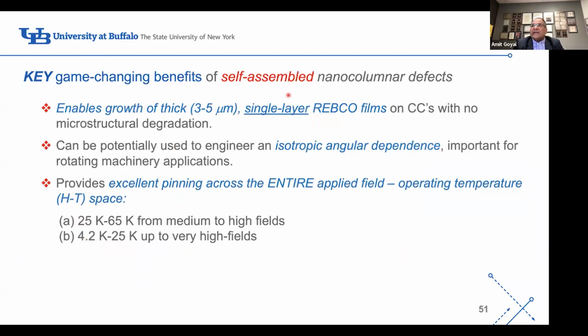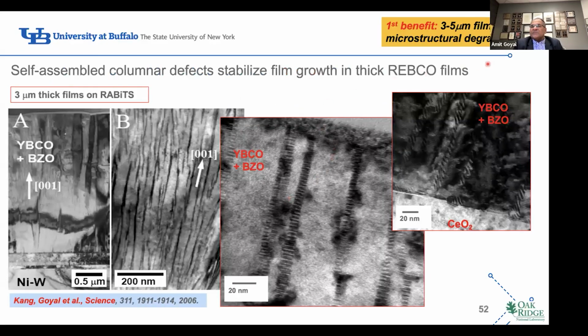But what this allowed us to do for the first time when we had this microstructural modification, first, it allowed us to grow very thick films, which is very important for high current. It allowed us to create isotropic angular dependence, meaning you could apply the magnetic field in any direction you want from 0 to 360, and you could have the same current carrying ability. And it allowed us to create, in addition to the linear defects that I showed you, point defects, which are really important for lower temperature applications. So first benefit, 3 to 5 micron films with no microstructural degradation.